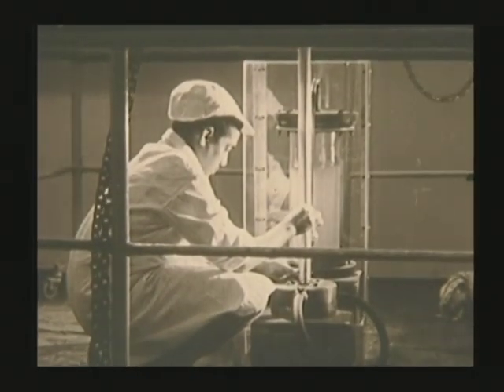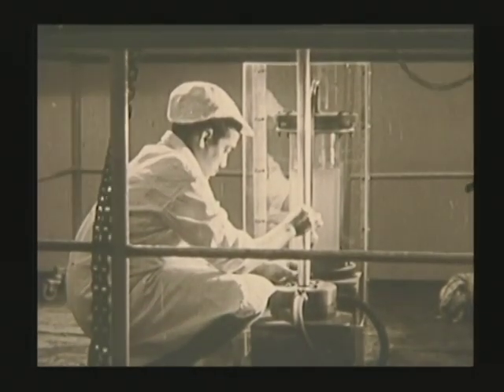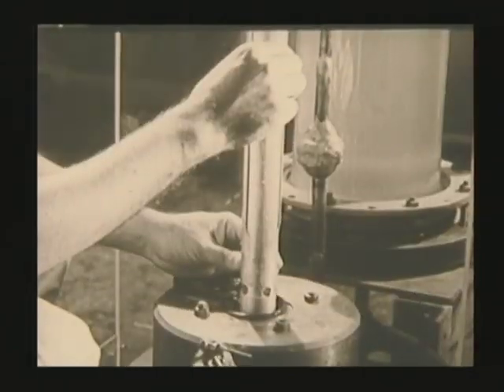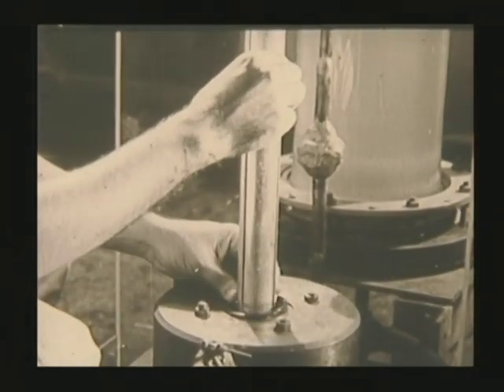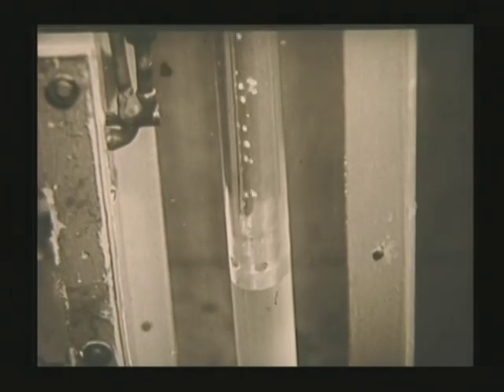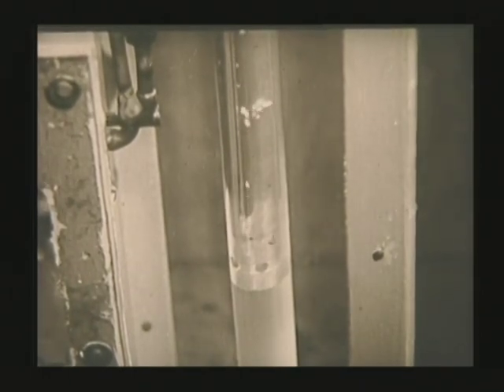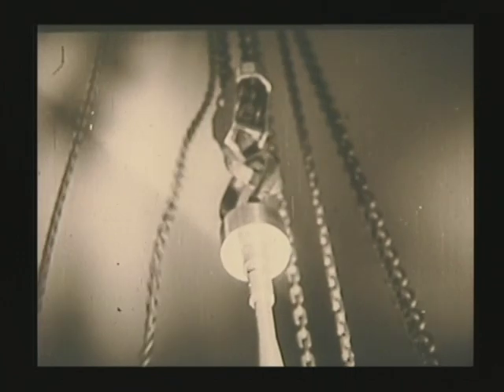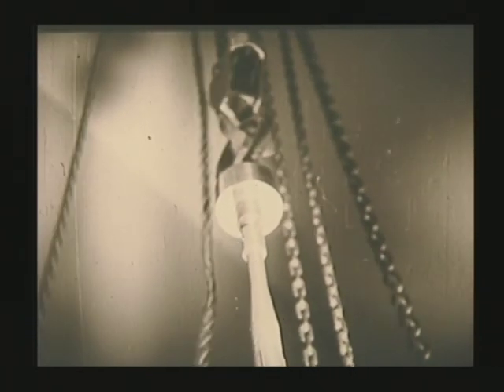A glycol test is then conducted to detect any pinholes or cracks in the sheath and porosity in the welds. In this test, the fuel element is immersed in glycol and then vacuum applied. Bubbles in the glycol indicate a fault, so this rod has to be resheathed. These rods are faultless and ready for use in reactor.